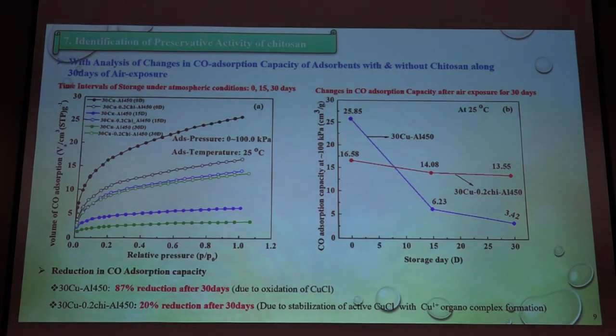Firstly, I exposed the sample to the air for 30 days, and at each stage of 15 days, I checked the CO absorption isotherm. So it was clear that after the 30 days of air exposure, the blank sample without chitosan lost its initial absorption capacity. But the chitosan-modified sample moderately maintained its initial absorption capacity, with only a 20% reduction in CO absorption capacity.